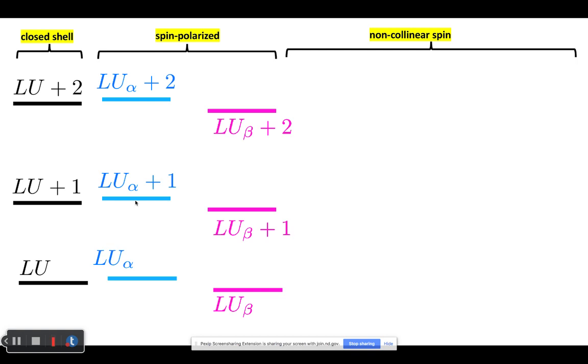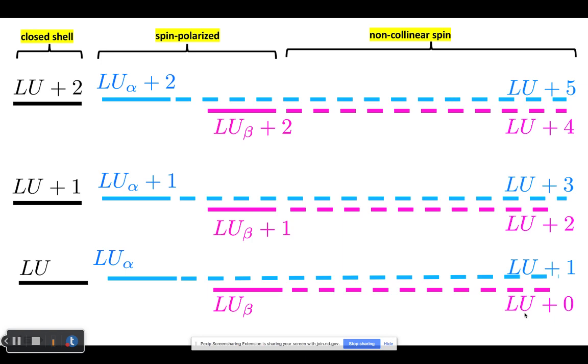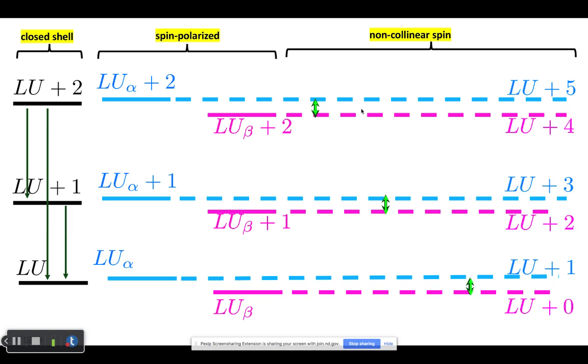non-collinear spin basis. Then the total number of orbitals is 6 as for spin polarized, but they are counted in a continuous way. So whatever was LUMO for beta is LUMO for non-collinear, whatever was LUMO for alpha is LUMO plus 1 non-collinear, and then it goes 1, 2, 3, 4, 5, total 6. So we can survive it. But in addition to electronic structure, we also have transitions, optical and non-radiative, right? And it is expected that if there is a larger count of orbitals, there is a larger count of transitions. So those transitions are qualitatively different. And some of them were not available if you do not include non-collinear spin treatment.